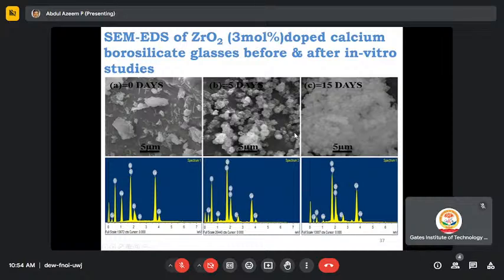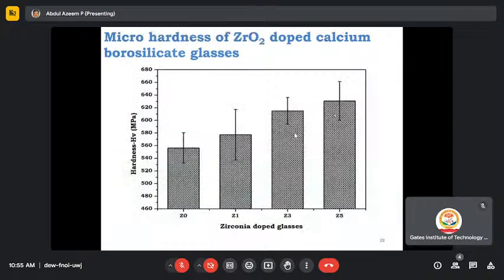This is before immersion. This is after immersion of 5 days and 15 days. So if you see the 15 days of immersion, you can see the precipitate. Why precipitate? This is the clear evidence of the formation of a layer on the surface of our material. So we can say that your material is bioactive in nature.